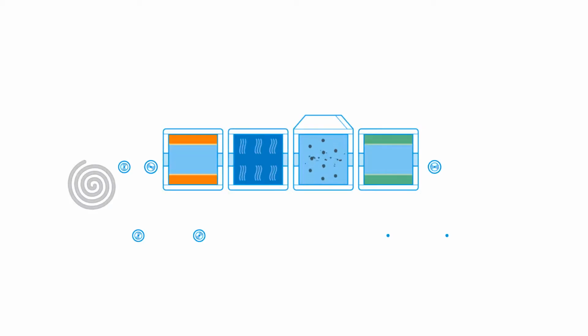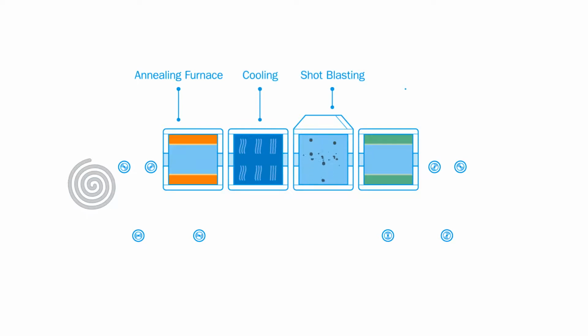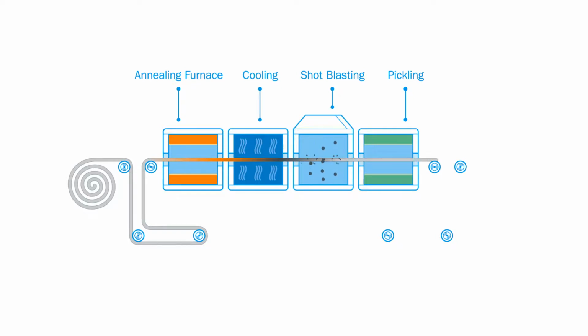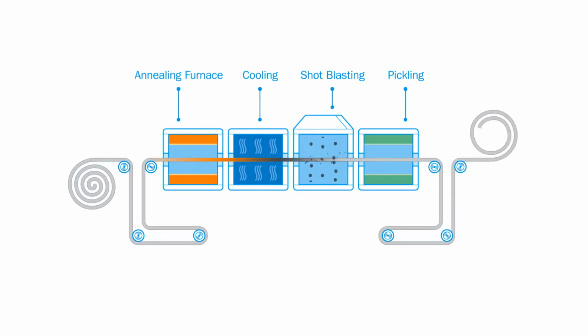Coils produced by the hot rolling mill are covered in black scale. In the cold rolling plant, coils are unrolled and passed along an annealing and pickling line, which recovers the mechanical properties of the steel, removes the scale, and changes the steel surface from dull black to silver grey. The acids used in the pickling process are recycled through acid recovery.